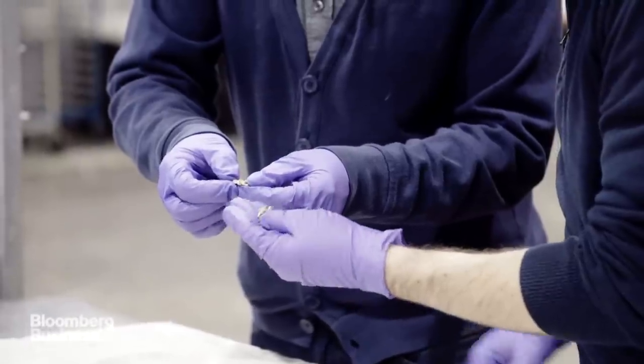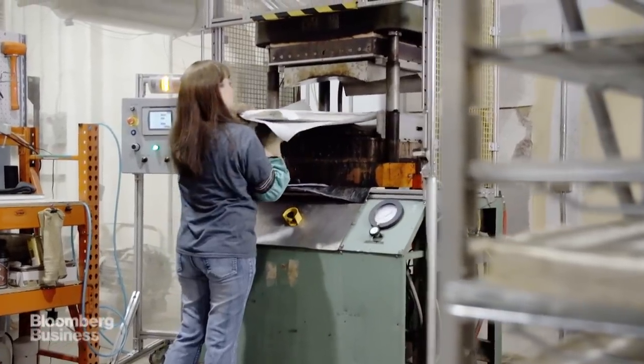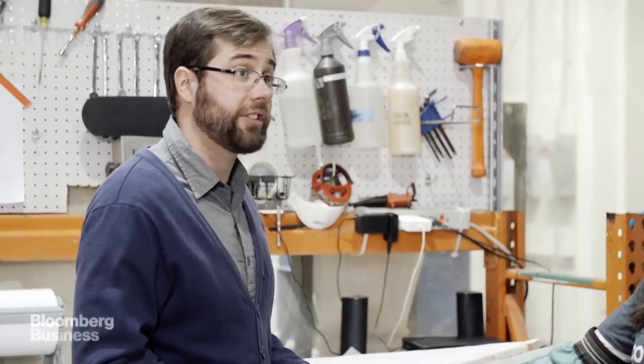How long did it take to get from basically raw ingredients to this? This panel here grows for four days — this is day four, so this is ready to go to our press. What the press is going to do is consolidate or squish this material down to a thickness that could be used in the furniture industry. It's removing any of the remaining water, killing the fungus, but also increasing the stiffness exponentially to a range where you would see traditional wood products.